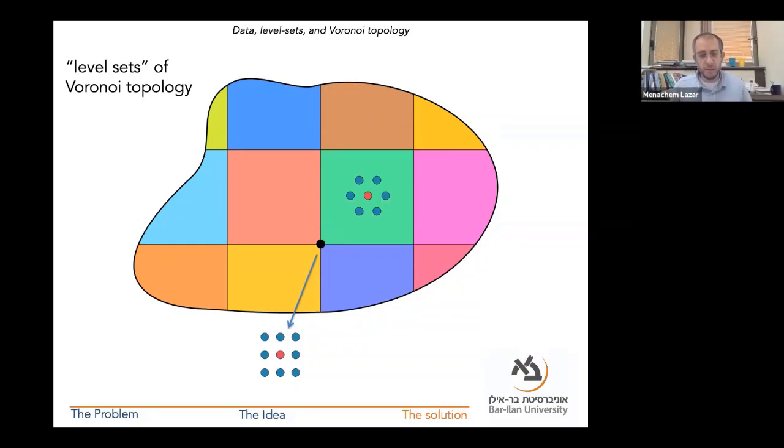So you have this certain arrangement of particles. This is in 2 dimensions, and in 3 dimensions you have a similar story, where infinitesimal perturbations, or almost all perturbations, will result in changes in the topology. Instead of having that one square in the middle, you could end up in the green, red, blue, or light orange section and have a different classification. But by itself, that's not terrible. What we could do is associate all of those regions, at least in theory, with a square crystal, with a square lattice.